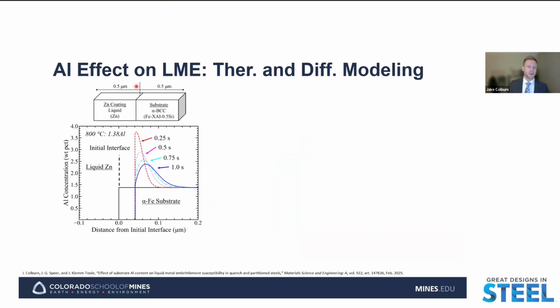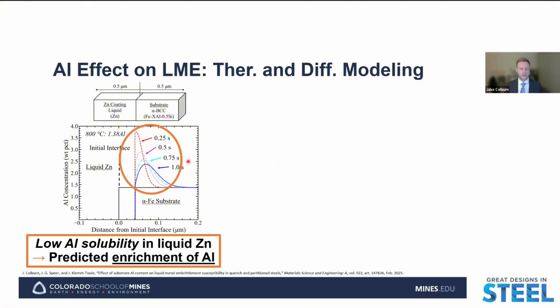And again, if we want to try and understand somewhat how the aluminum in the substrate is potentially affecting what phases are present at the interface and affects that local composition, we can start again by looking at our diffusion couple, again, of liquid zinc here on the left, an aluminum silicon containing iron phase on the right. And we see that after simulating at 800 degrees C for 1 second, we again, like silicon, see this potential enrichment of aluminum at the interface due to the low solubility of aluminum in the liquid phase as compared to iron.